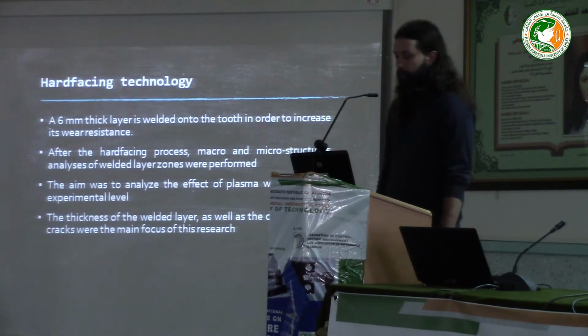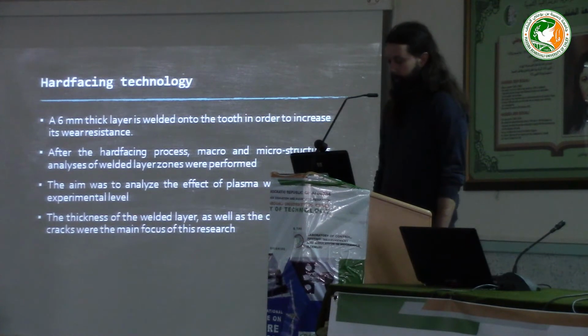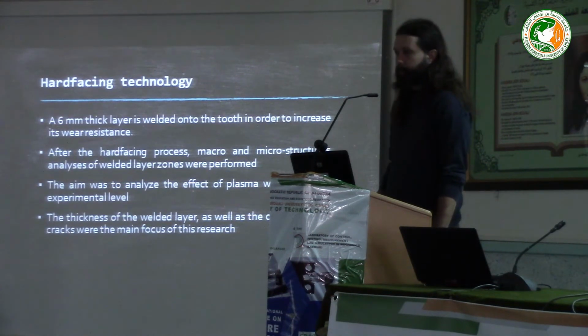So as I have mentioned, the goal was to create a welded layer with a thickness of 6 millimeters on the tooth in order to increase its wear resistance. Once the hard-facing process was complete, the structural and microstructural analysis of the welded layer zones were performed. And this was achieved by cutting the tooth model in half, but that will be explained a bit later. The idea was to analyze the effect of plasma welding on an experimental level to see where the cracks are initiated and how they are distributed. So the most important aspects that were researched here were the thickness of the welded layer and the distribution of the cracks, especially in the microstructure.